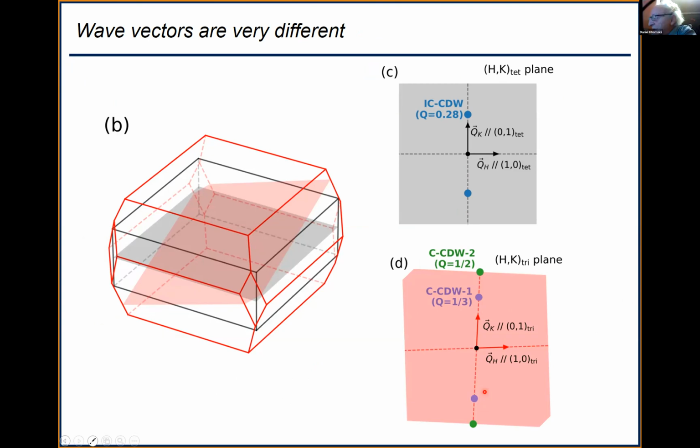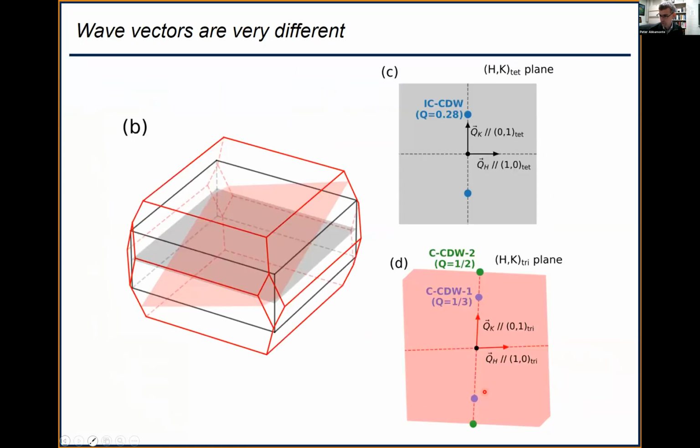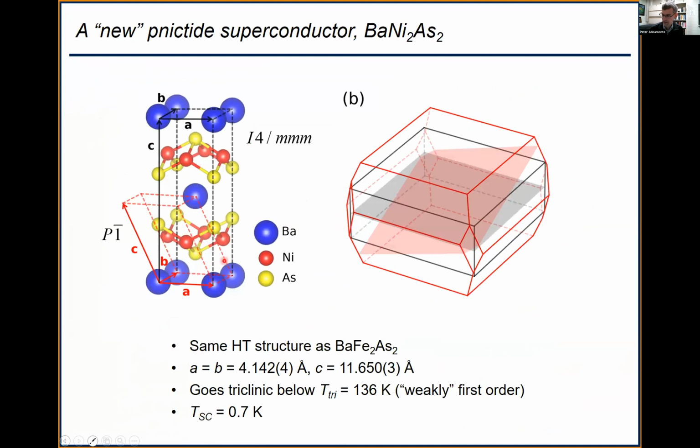So isn't it possible that that's exactly why it's really different? Because if I understand from the first talk, in the triclinic phase, the distance between layers becomes much smaller, so the system becomes essentially more three-dimensional. Is it possible? I don't think so. The size of the change is very tiny. The structural displacement is very small. I don't know about the dimensionality. JP may have some anisotropic transport data that I haven't seen, but when the unit cell that you pick changes hugely, the atoms don't move much. So the angles change a very tiny amount. I forget how much when you go from tetragonal to triclinic. You just pick a different cell when you describe the diffraction because you have to.